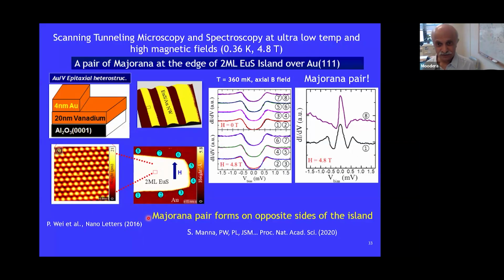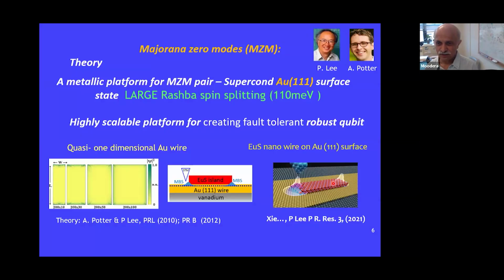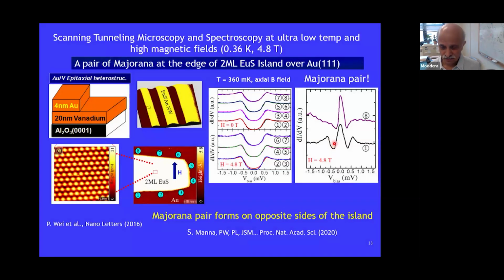So if you look at the previous slide, you see this Majorana mode, it acts like a state. So we should be able to see in the tunneling spectroscopy these states evolving as a function of magnetic field. In zero field, of course, you don't see that state in any location all the way around. But when you apply a critical field, then you can see the energy gap in all these places. There is no Majorana mode. And only in these two locations, you can see this Majorana mode.